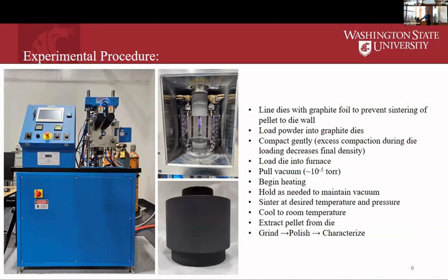In our particular case, we use hot uniaxial pressing because it's a pretty tried and true method. It's relatively simple, and it's a lot faster than vacuum sintering, which can take many hours and be very energy intensive and expensive. The general process flow is that you have a die, and you line your die with some type of foil to prevent your powder from sticking to the inside of the die after the sintering process.